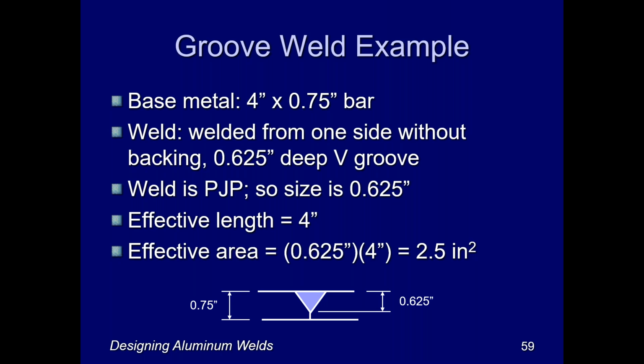So this weld is a PJP because I didn't use a backer, and the size is 5/8 of an inch, the depth of preparation. The length is 4 inches because it's a 4-inch wide bar, and that makes the effective area 2.5 square inches.